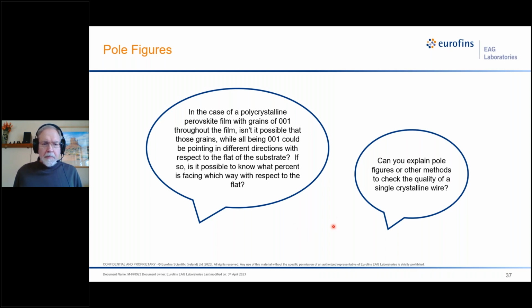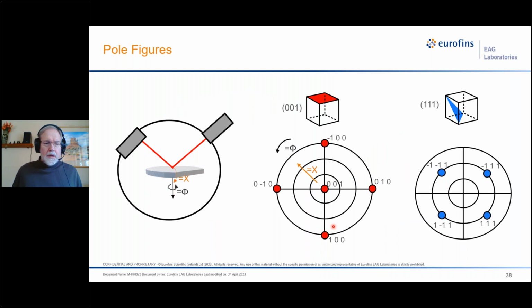So at each angle, we're going to do a full 360-degree scan in phi. We're sitting at the X-ray peak location of the plane that we're interested in. We're fixed at that position. So in this case, the 001 location, we do a scan in phi, we tilt the sample 5 degrees, we do another 360 in phi, and you gradually build up a pattern.